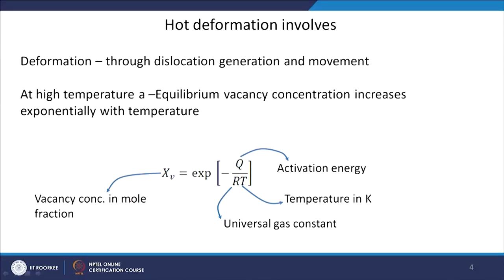At higher temperatures, another important thing is the equilibrium vacancy concentration. At any temperature above 0 K, you will have some vacancies in the material — vacancy is a thermodynamic defect, so it will always be present. The equilibrium vacancy concentration changes as a function of temperature exponentially, so as you keep increasing temperature it increases exponentially. Vacancy concentration (in mole fraction) is related to activation energy for vacancy formation and temperature. Activation energy is constant, so as you increase temperature there is an exponential increase in vacancy concentration.